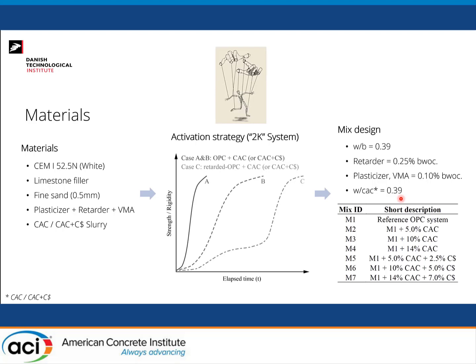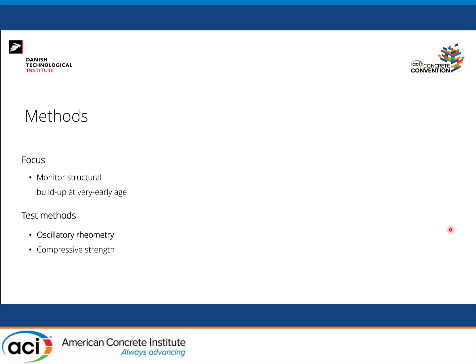We want to avoid clogging, which is typical when you're playing with much faster accelerating methods, like the use of shotcrete accelerator, for example. And then we tested this base composition activated with different slurries, again pure CAC, and then CAC and calcium sulfate at different dosages, in order to map the curve of evolution of structural buildup over time, and then pick one of the mixes as a candidate for printing.